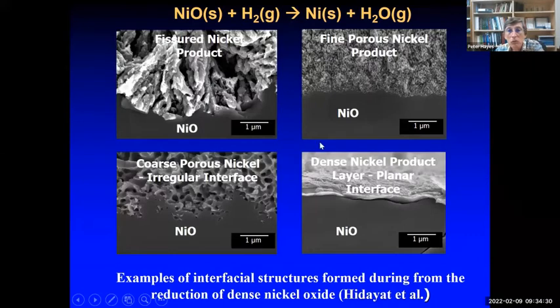So let's go back to the structures we saw in the nickel oxide hydrogen system, and here's some examples of the microstructures. So here's the dense nickel layer product. You can see stopping the gas getting access to the nickel oxide underneath. Here's the irregular interface formed by the discontinuous growth. So it forms a dense nickel layer, which then breaks down, and we get the pores formed again, and then gets covered again. So a cyclic process is a discontinuous process.